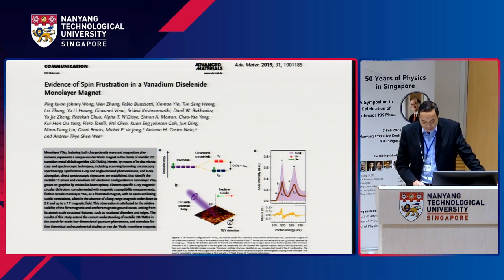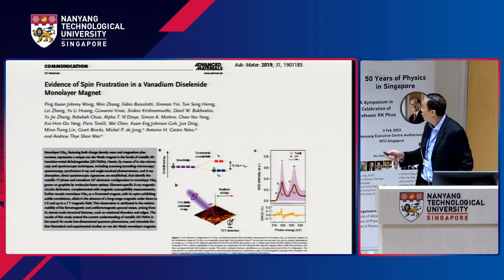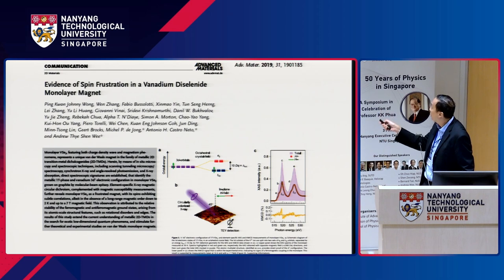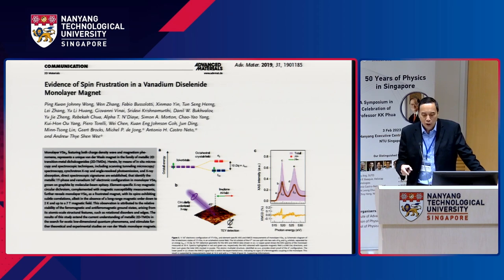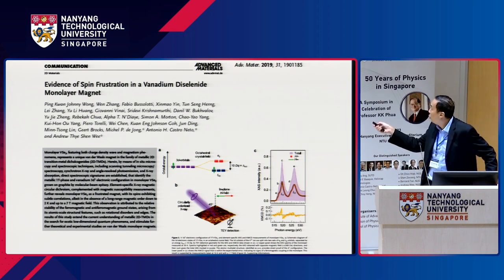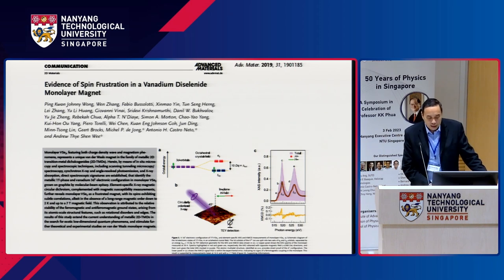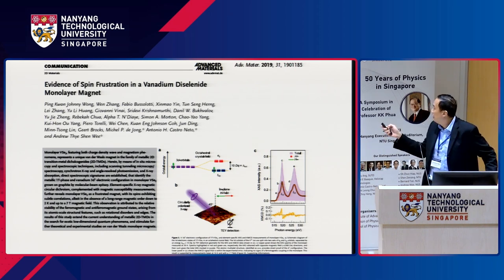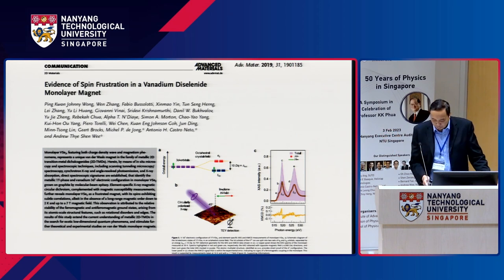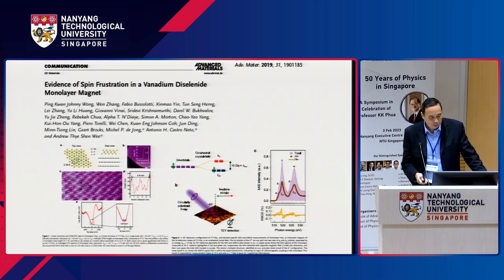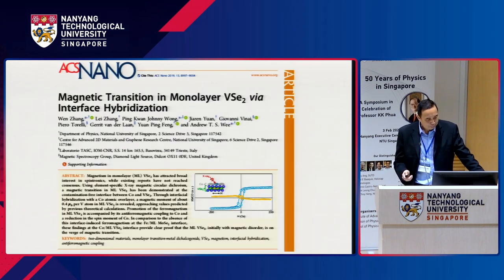And the main technique used then was the synchrotron method, which I'll show here. This is X-ray absorption. This is a dichroism method. That means you're basically taking the X-ray absorption using clockwise and anti-clockwise circularly polarized synchrotron beams. So from the signal, which is very small, you can infer that at least for the vanadium ions, this material is probably non-magnetic. That's just the STM, charge density waves of the material.